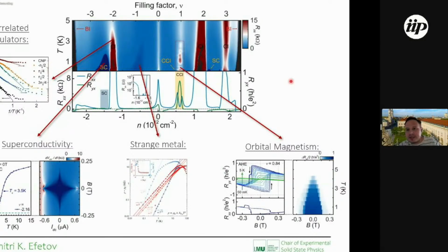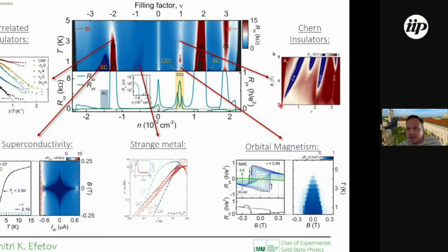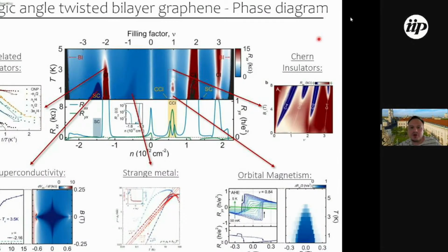And moreover, what you can already see here, or at least guess, is that this Hall signal at 0 field is close to being quantized to h over e squared. So it's close to one quantum of conductance here. And this is not perfectly quantized because probably the device is disordered, but really it's striking that it is almost quantized. And this is basically the Chern insulator feature, which we also observe more clearly at slightly elevated magnetic field. And those Chern insulators are basically topological states, which sometimes persist down to 0 field, which are then 0 field Chern insulators, or topological insulators, as you like.